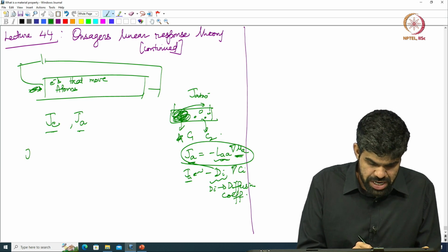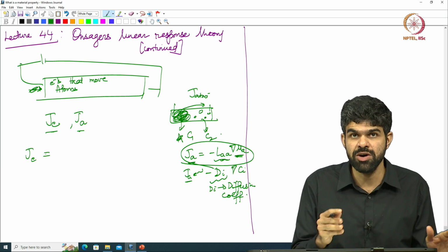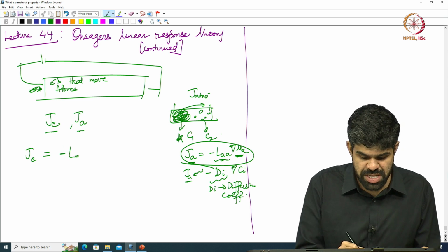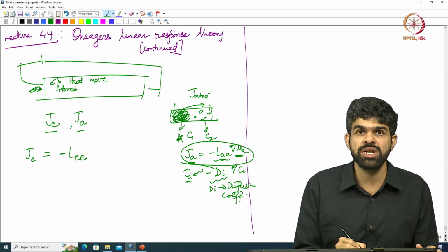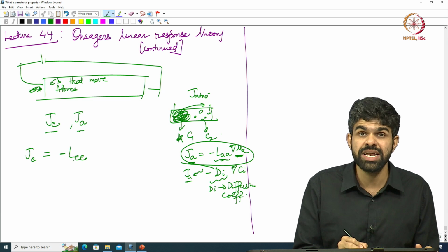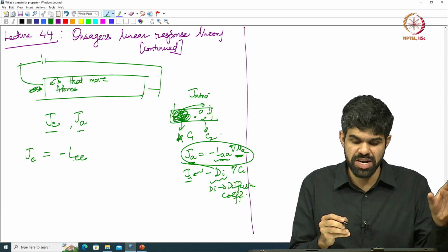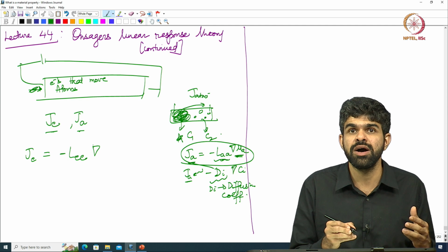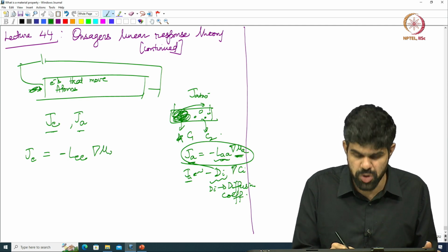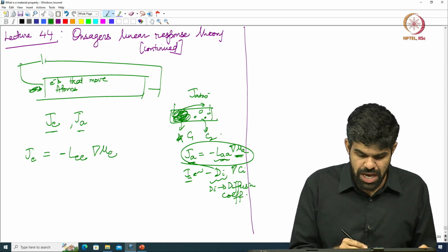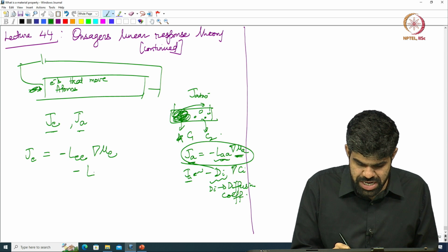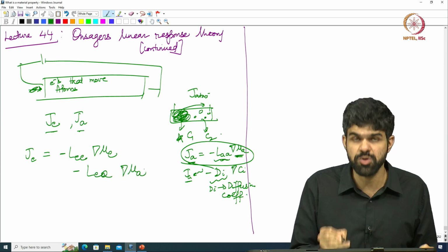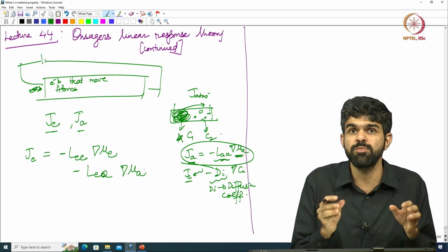Now let me look at how the electrons are going to move around. There is going to be a flux of electrons, and this is a direct coupling of electrons. Electron flux can be created if I have a gradient of electron chemical potential, and it can also be created if I have a gradient of the chemical potential of atoms.